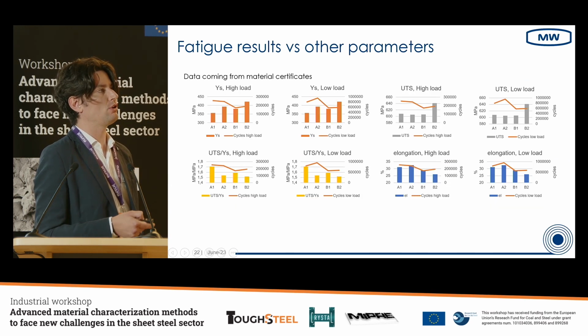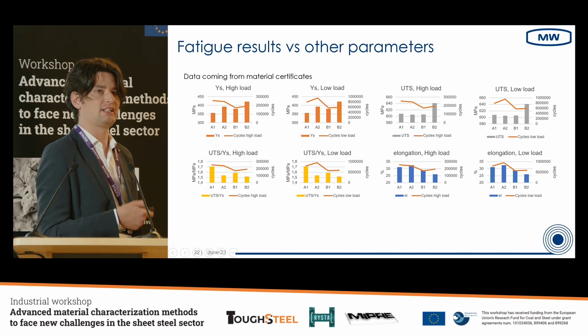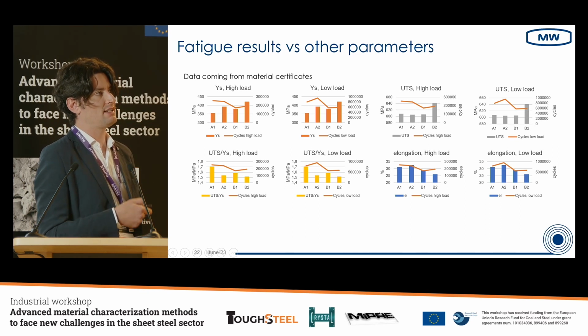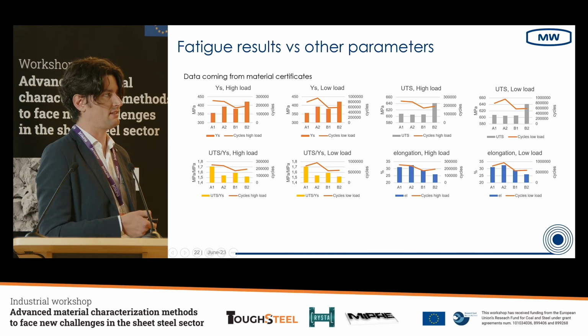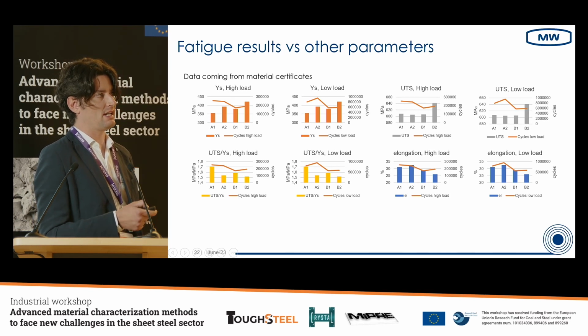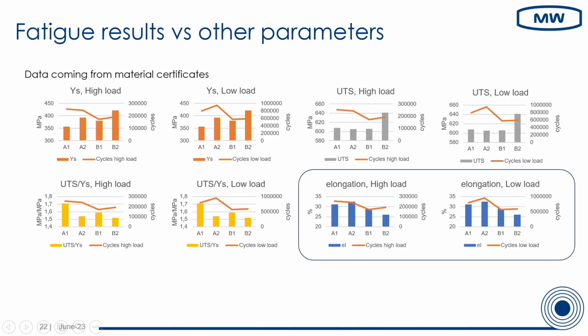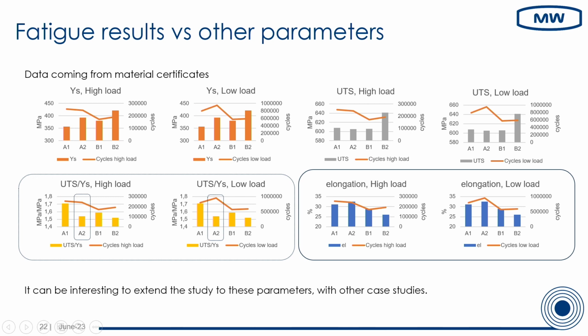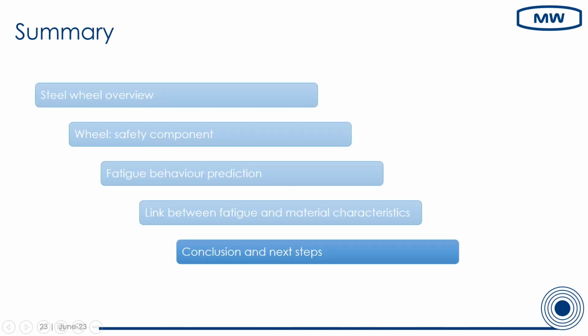Then we also analyzed other characteristics coming from the material certificate, like yield stress, UTS, the ratio between yield stress and UTS, and the elongation. And there is also in this case quite a good correlation with the elongation, and there is also a small correlation in this ratio, except for the material A2. So it can be interesting to extend this study to other parameters and with other case studies.